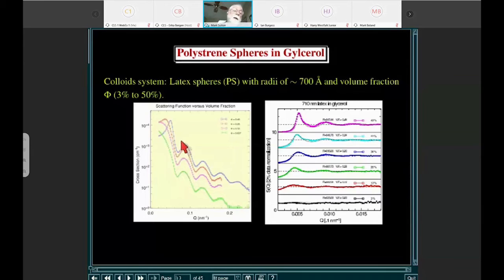As we increase the concentration, the particles start to get correlated with each other, and basically the blue curve occurs at 49% volume fraction. So we know the small angle scattering is the product of 2 terms. One term is the scattering of the particles, and the other term is to do with the structure factor, or the correlation between the particles. So if we simply take the green curve, which is a good measure of the independent particle scattering, and divide it into the rest, we can measure the S of Q. And that's what's shown on the right here.